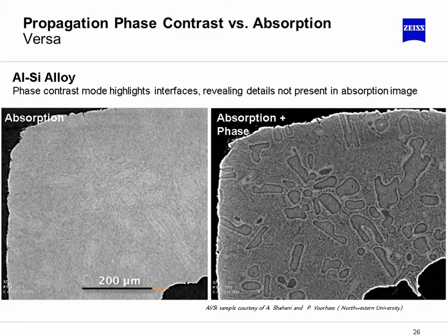Now, moving along, I mentioned phase contrast. This is an example of an aluminum silicon alloy, which conventionally has very little density difference between the two domains. And when you place the microscope in a phase contrast condition by moving the source and the detector away from the sample, increasing that propagation distance, the definition of the edges becomes much more clear. And even in this case, you can see some of these fine needles or plates, which are indicative of the eutectic structure within the aluminum matrix here.